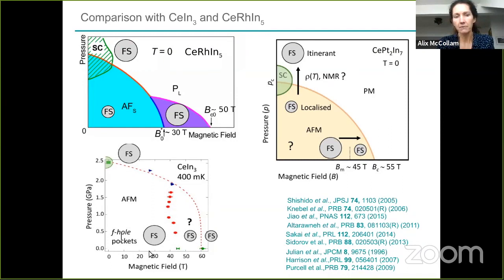Going in this direction as a function of magnetic field, the Fermi surface is small, so localized f-electrons in this region, and it's not clear. There is a feature in the, I think this is the magnetic susceptibility perhaps, or magnetization of cerium indium 3 here, and it's thought that this could be a change in the Fermi surface again within the antiferromagnetic state. But this time it's going the other way, from large to small. So it's not a consistent picture across these materials. And then this is cerium platinum 2 indium 7.